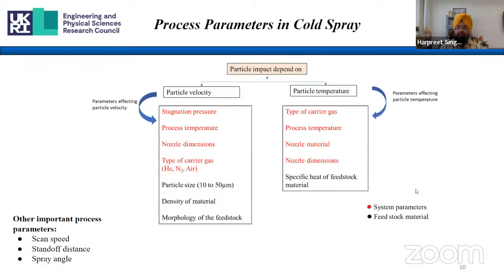Now, what are the major process parameters in cold spray? As we know, as the particle will impact on the surface, two things are important. One is particle velocity, another is particle temperature. These are the parameters of cold spray which will affect our particle velocity. For example, stagnation temperature, pressure, process temperature. As I said, pressure and temperature will help us achieve higher velocities, along with nozzle dimensions, type of carrier gas, and so on. Helium is quite interesting, quite a lighter gas, can give us very nice critical velocities, but again, it comes at a price, so we have to have some other options.